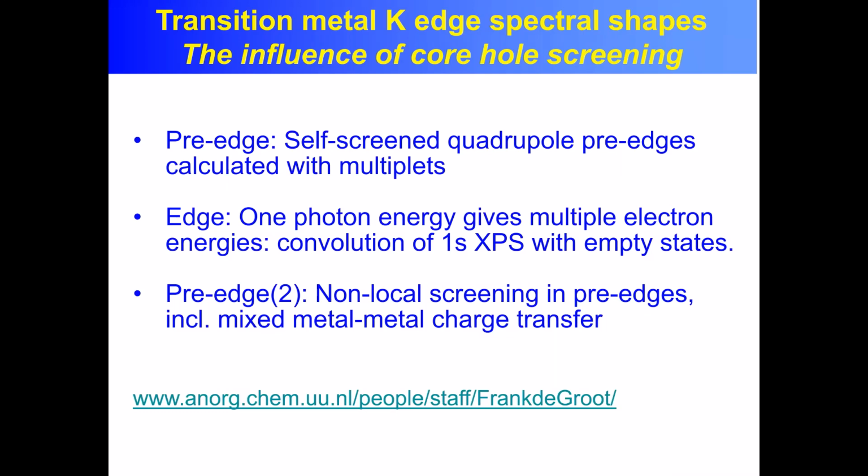So what would be the manifestation of this in the XANES? That's difficult. In general, the Jahn-Teller effects are small in energy, so they will be difficult to see in K edges, I guess, or even in L edges. But indeed the non-local screening effects will be very interesting. They should be very large in principle in these systems. Okay, thank you.